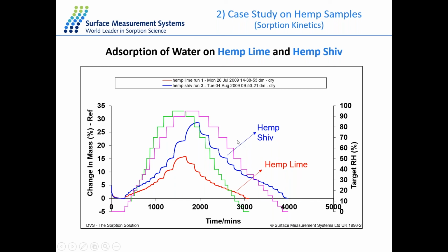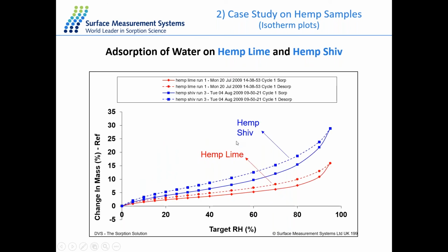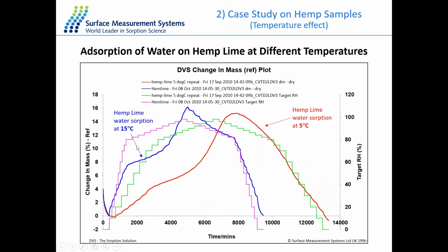And from the isotherm, it's also clear that the water capacity decreases almost 50% when the hemp is mixed with the lime binder. And this is because the binder will go into the pores of the hemp, blocking the pores. This will result in the lower water capacity. So this kind of hemp-lime composite can also help to inhibit the growth of fungi or bacteria in the wall because of the lower water capacity. And here it just shows the moisture sorption at different temperatures on the same hemp lime sample. And you can see at 15 degrees, it has a much faster equilibrium compared to the 5-degree one. And this also indicates the improving of the thermal insulation behavior of this kind of hemp lime composite.